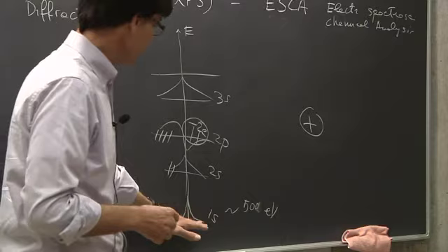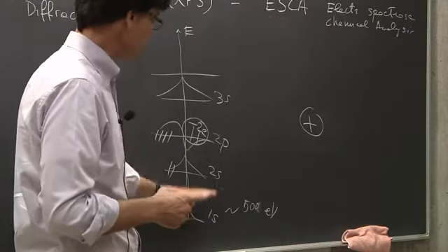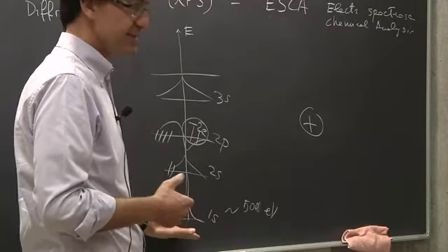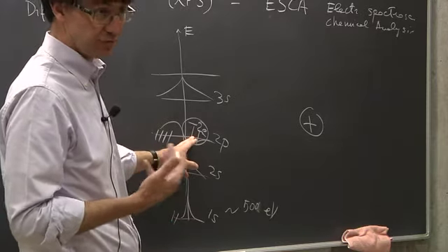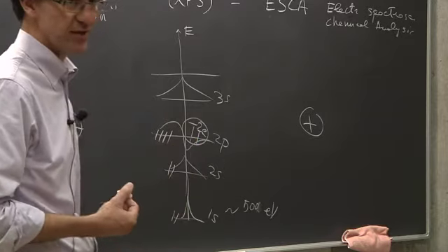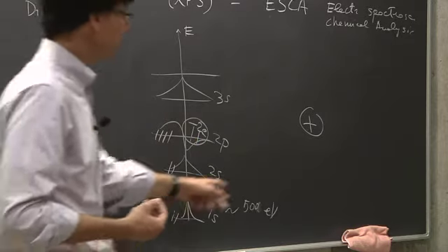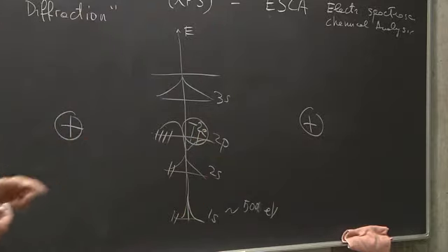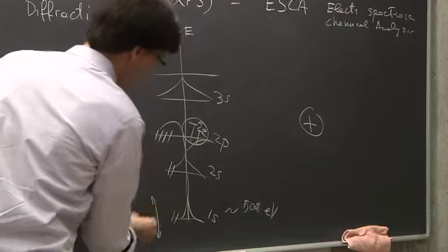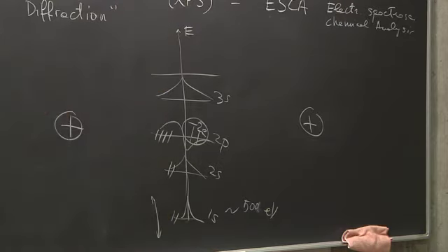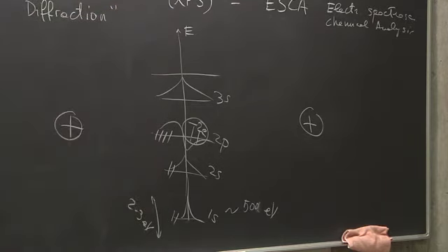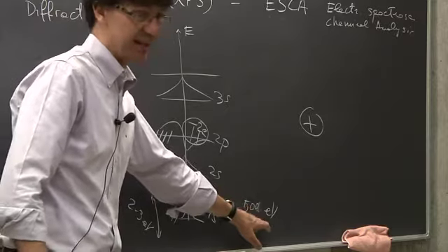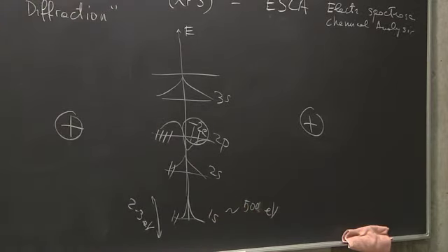All right? So the position of the electrostatic potential of this 1s state depends heavily on the charge state, the valence state, of the oxygen itself, and also on the position, distance, and charge state of the nearest neighbors. And the changes due to this electron transfer can be of the order of 2-3 electron volts. Of course, this is very small compared to the binding energy of the 1s state, but it's still not negligible.